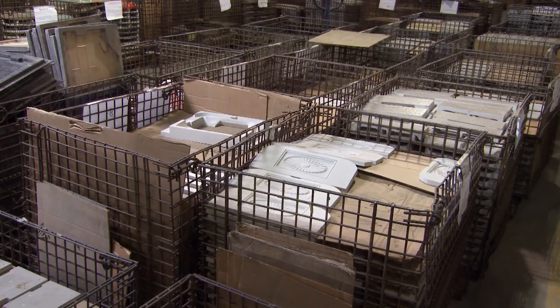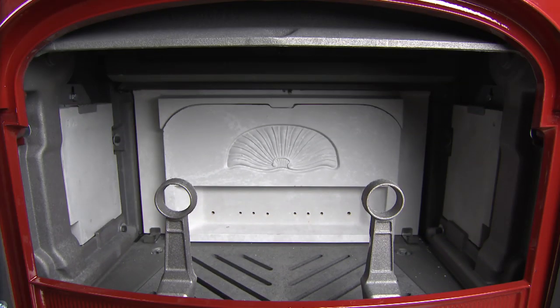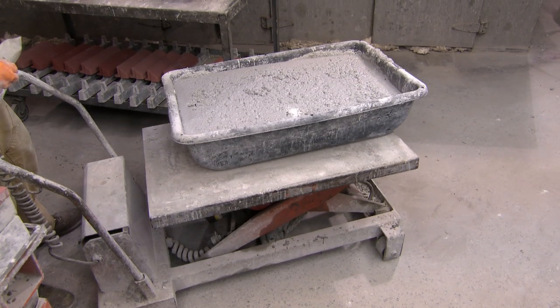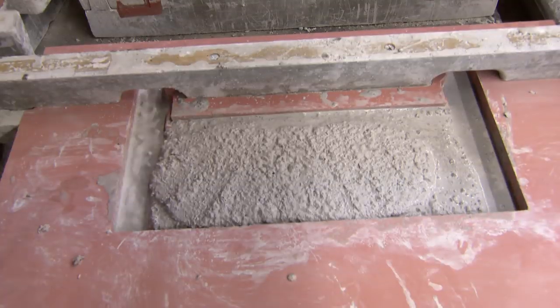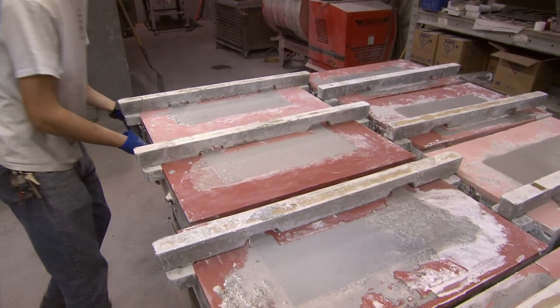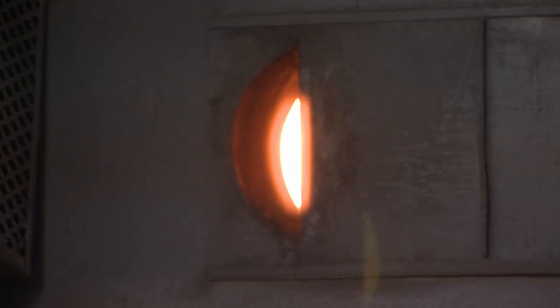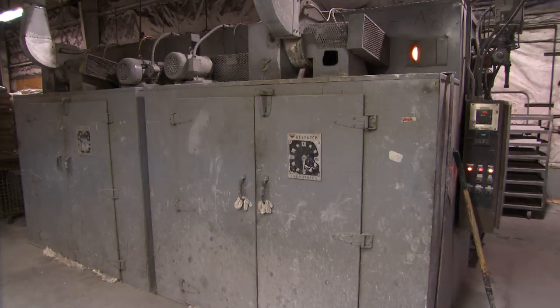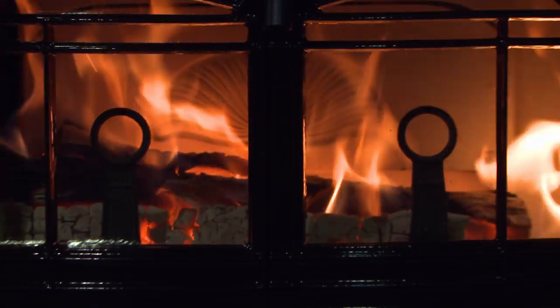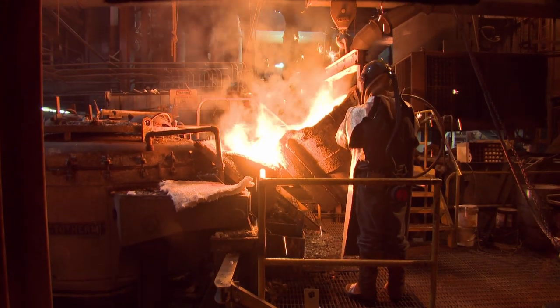In another part of the plant, they make something called the refractory — a ceramic liner that prevents the iron stove from burning cherry red when cranked up. It's made of fused silica that can withstand temperatures up to 3,200 degrees Fahrenheit. It's poured into rubber moulds, air-dried for 24 hours, then baked at about 600 to 800 degrees for six hours. The refractory is crucial to clean combustion, helping the re-burning of gases — and fused silica is the same material used to line the foundry furnaces.